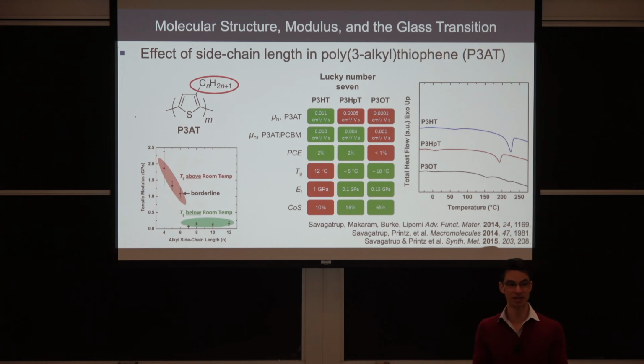Now, given the importance of the glass transition temperature in predicting the mechanical properties, you would expect it to be pretty easy to measure. But the problem is these materials are so rigid, and you already have all of this heat capacity tied up in these side chains, that when you look at the calorimetry data, so you add heat to the system as a function of temperature, and what you're looking for here is a change in heat capacity. So a change in heat capacity corresponds to the glass transition. Now these lines are all relatively flat, and we know that the glass transition occurs around here. It's pretty hard actually to calculate it.